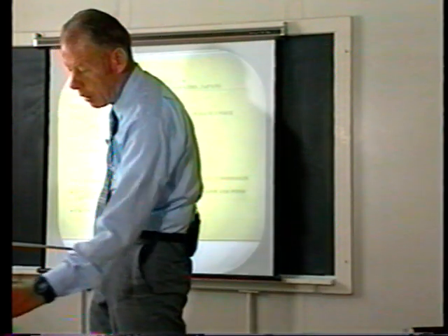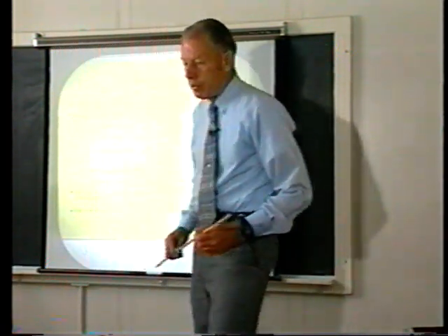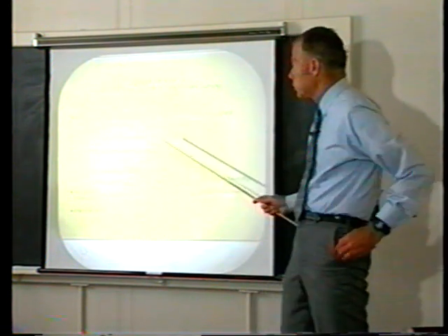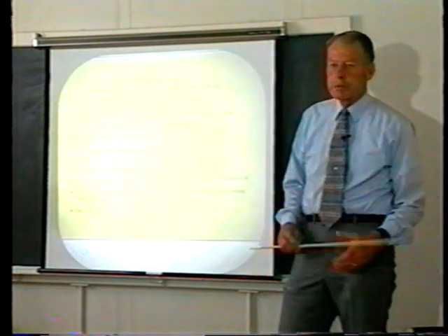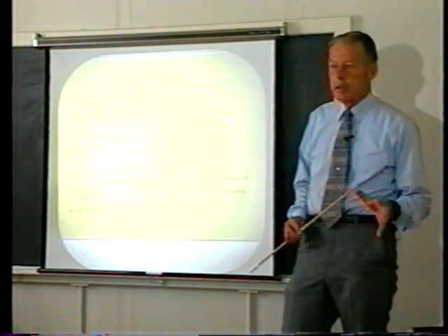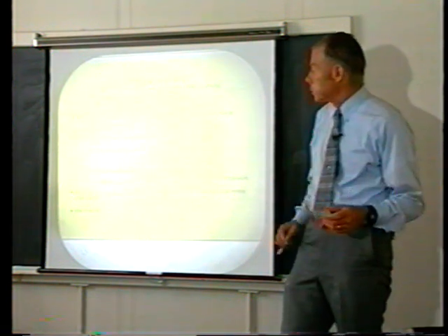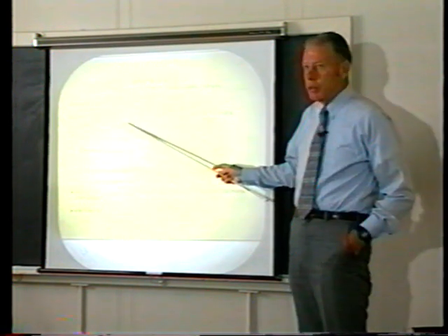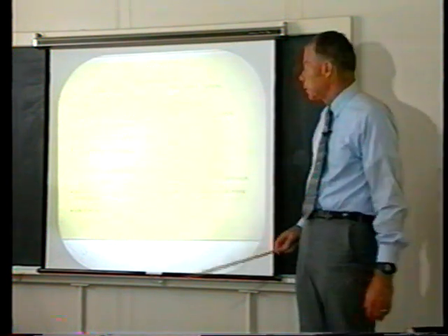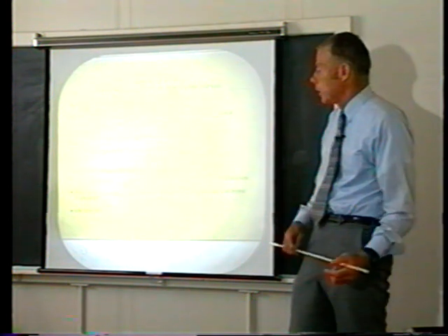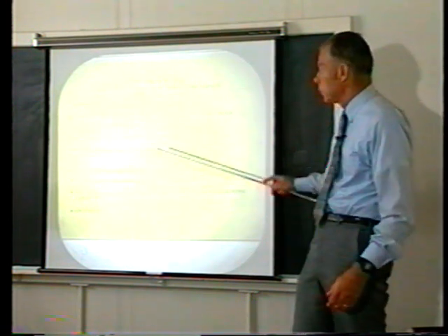Also at this cold fusion conference in Japan, Pons and others report on a new calorimeter they call the Icarus 9, designed to operate under boiling conditions. Fleischmann and Pons found that once you get the palladium loaded at low temperatures, then if you go to high temperatures, you get larger effects. So this calorimeter is designed to operate under conditions where the electrolyte is boiling, but yet it condenses and goes back down in the cell. He found excess heat in 3 cells out of the 8 tested, and he had a large excess power effect up to 200% of the input power.